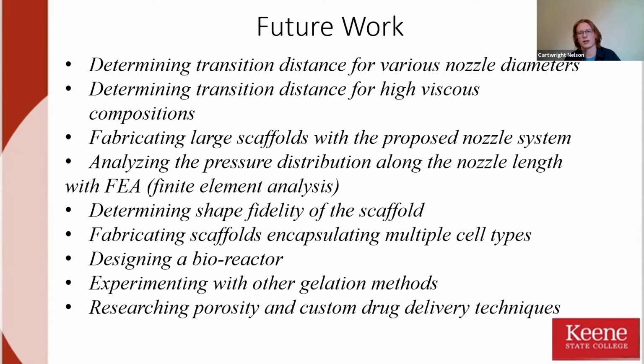I think most of them were 30 millimeters, and they don't get very tall because there's not a lot of structure, because if they do get too viscous, they require too much pressure to print. We're also going to analyze the pressure distribution along the nozzle length with finite element analysis, determine shape fidelity of scaffolds, and hopefully start fabricating scaffolds with encapsulated live cells with multiple cell types.